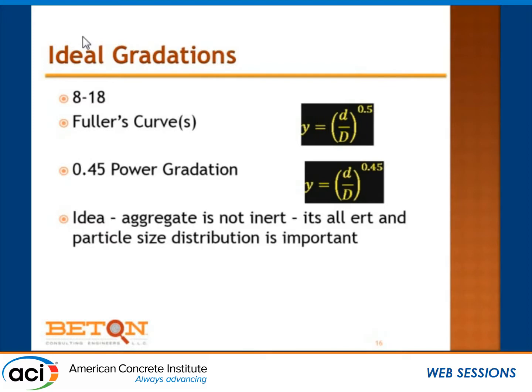And that, of course, we can go on and say, well, I want the maximum density curve. And Fuller had a number of curves. His curve of maximum density was that the particle size distribution is, with a maximum particle size of capital D, the individual size d, if you raise that to the 0.5 power, then you would get the maximum gradation. The Federal Highway Administration spent a great deal of money in the period right after the Second World War. They developed the 0.45 power curve, which said it's not 0.5, it's 0.45. It's always interesting to recall that both of them assume spherical aggregates. So if you see a spherical aggregate on occasion, which do happen if you make concrete with marbles or with taconite pellets, actually, then you can use these.